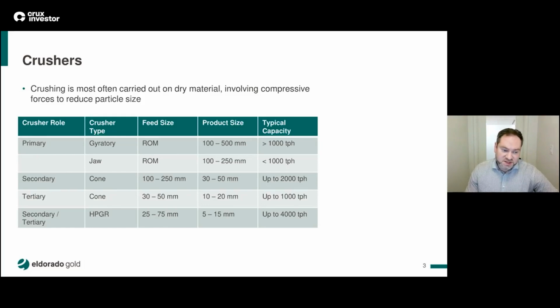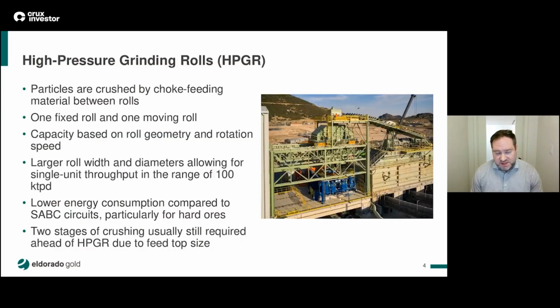Relatively new technology such as the HPGR has replaced secondary tertiary crushing in a lot of applications, and these units have become significantly larger in recent years. There's an example here of high pressure grinding rolls, and this is an installation at our Kışladağ operation in Turkey, where we replaced several tertiary crushers with a single HPGR unit ahead of a heap leach. HPGRs use one fixed roll and one moving roll to crush material between the rolls. This allows for very significant throughput and high compressive strength and a small particle size in a single pass, or they can be operated in closed circuit with a recirculating load.